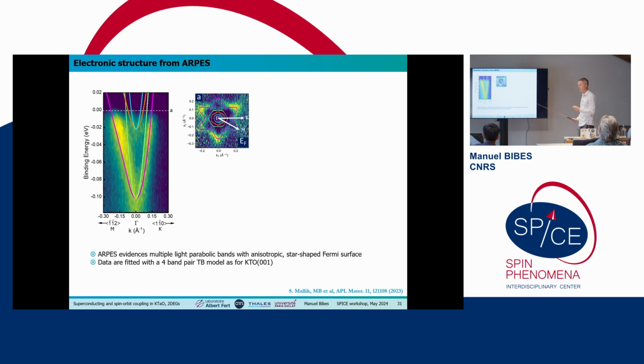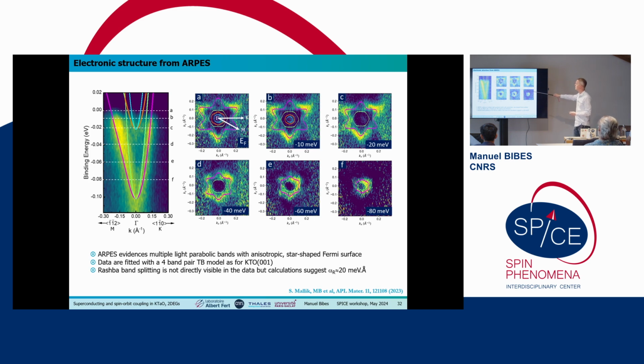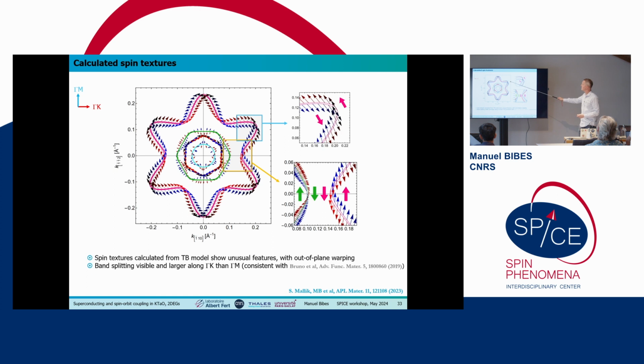We also did ARPES of the 111, and unfortunately the data are not quite as nice as for the 001. We were able to fit the data with a tight-binding model, again inspired from the one we had for KTO 001. Here we do not see direct evidence of Rashba splitting, but taking into account all the different parameters, we can see a little bit of splitting from the fits. And we think the minimum value is about 20 millielectronvolt angstrom, which is quite small. You can see here the spin textures from these different bands, and there's a small separation here and there, and some anisotropy of the Rashba coefficient depending on the direction, gamma K or gamma M.